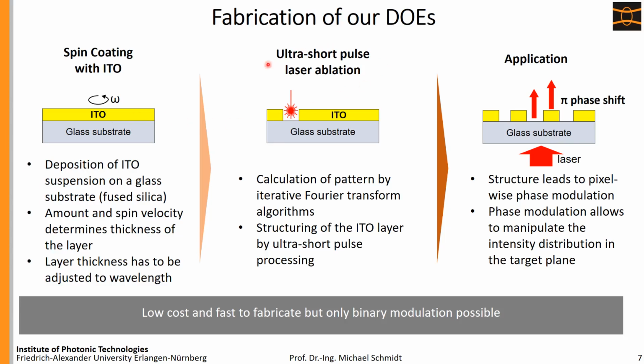Then we use ultra-short pulse laser ablation to make a pattern there, and the pattern is defined using a Gerchberg-Saxton iterative Fourier transformation algorithm that we calculated before. And then we use all this to shine our laser light through the glass substrate, and where there are rests of the ITO layer, we get a pi phase shift, so our lambda half phase shift. And by this we have a phase mask, allowing phase modulation, and have a phase hologram to program the shape of our beam on the target plane that we want to have.